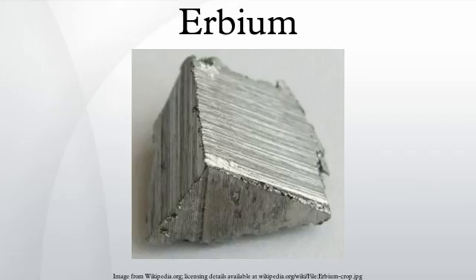An erbium-nickel alloy Er₃Ni has an unusually high specific heat capacity at liquid helium temperatures and is used in cryocoolers. A mixture of 65% Er₃Ni and 35% Er₀.₉Yb₀.₁Ni by volume improves the specific heat capacity even more. A large variety of medical applications utilize erbium-ion 2940 nm emission, which is highly absorbed in water. Such shallow tissue deposition of laser energy is necessary for laser surgery and the efficient production of steam for laser enamel ablation in dentistry.